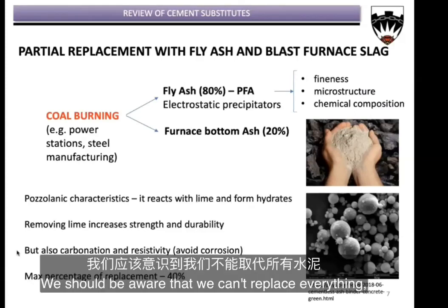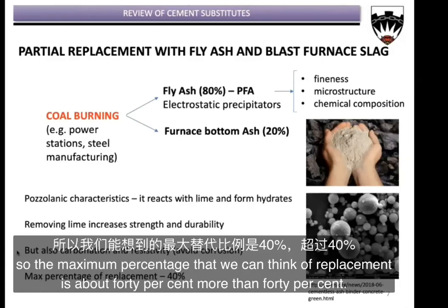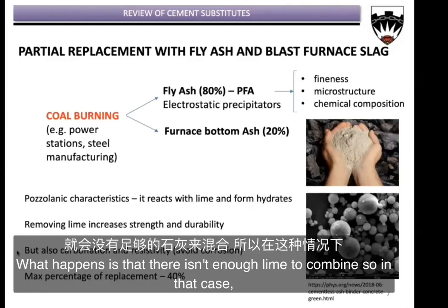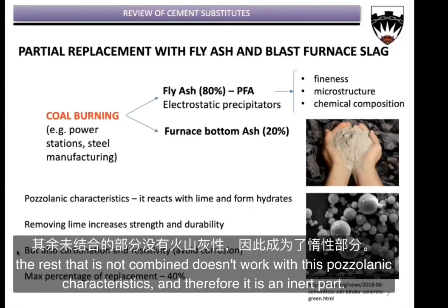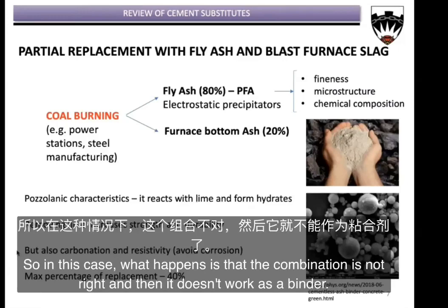We should be aware that we can't replace everything, so the maximum percentage of replacement that we can think of is about 40%. With more than 40%, there isn't enough lime to combine. So in that case, the rest that is not combined doesn't work with these pozzolanic characteristics, and therefore it is an inert part. The combination is not right, and then it doesn't work as a binder.